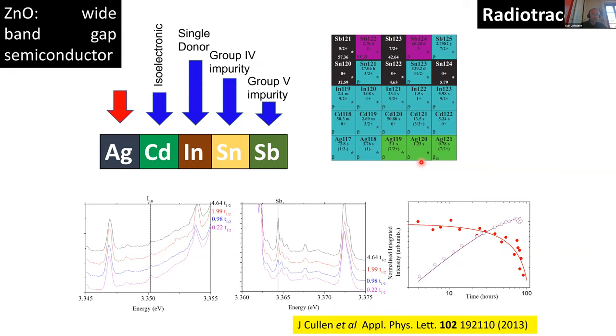Just one result from radio-tracer photoluminescence. This activity is beginning to start up again for the physics program next year. We were looking at optical features related to donors inside zinc oxide. We implanted a very short-lived silver beam with a half-life of only 0.78 seconds, which decayed through cadmium, indium, tin, and finally to stable antimony. We were able to unravel the nature of tin donors inside zinc oxide and discovered the first antimony-related optical feature in this material.